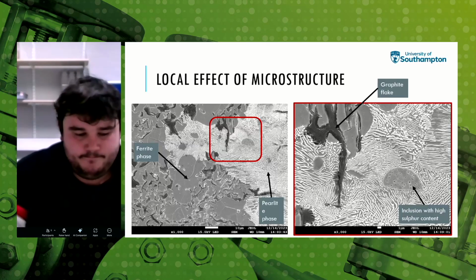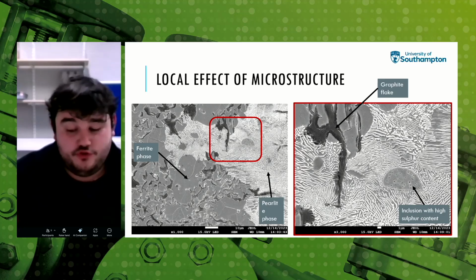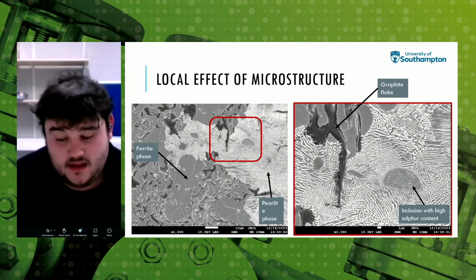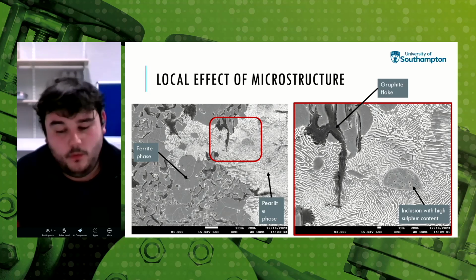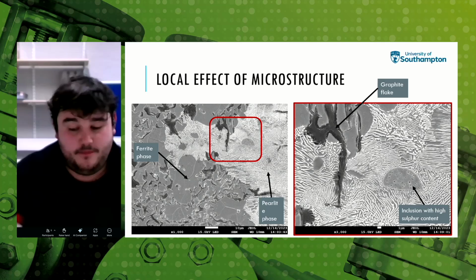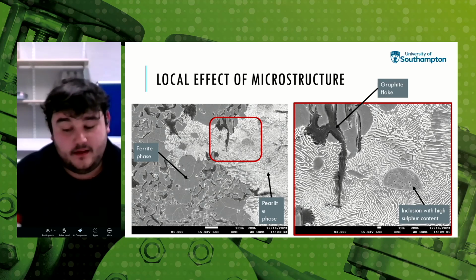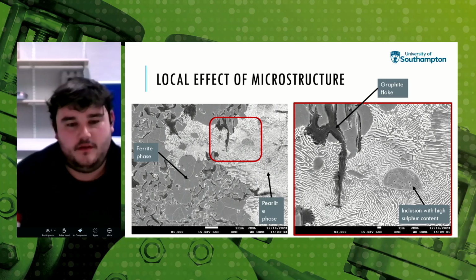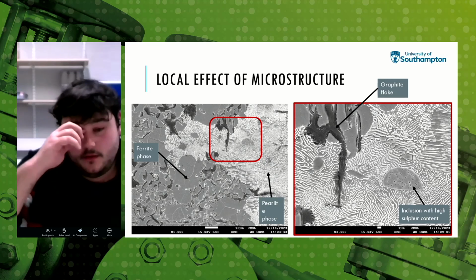As we discussed earlier, another crucial factor is the orientation of these graphite flakes. As you see on the screen, the crack growing down through this sample will be easily able to propagate through this pearlite phase, as there's a graphite flake that runs perpendicular to the phase and encourages that crack to split open that pearlite phase.